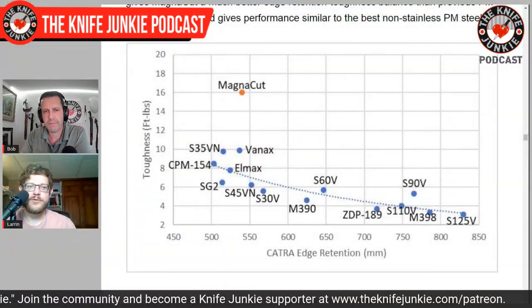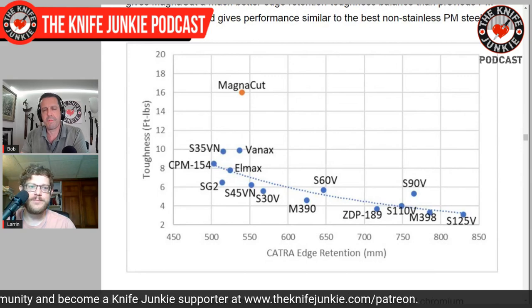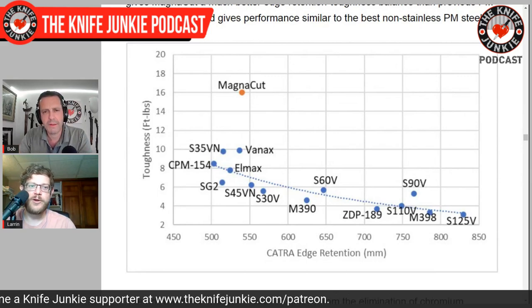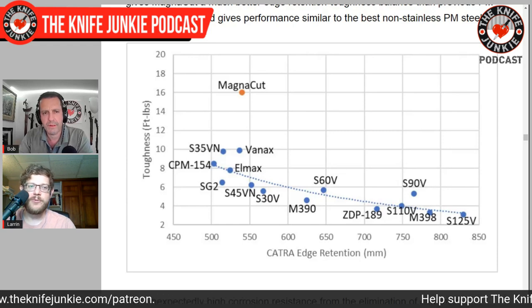Yeah, it's all about balancing the elements. So like D2, for example, it's a non-stainless tool steel. It has more chromium in it than MagnaCut, but it is much less corrosion resistant. And it's because it has too much carbon to be a stainless. So you add more carbon and it makes the chromium more likely to form a carbide. It's pretty simple. Chromium and carbon make carbides. So if you keep putting more carbon in there, eventually that carbon will start eating up your chromium instead of allowing the carbides to dissolve in your heat treatment.